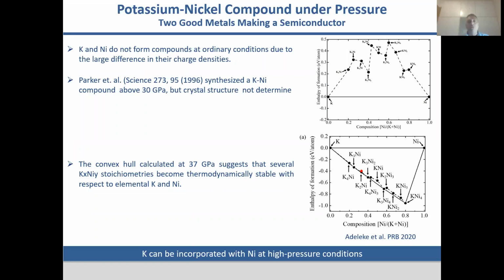Under pressure, we know that there is an s-to-d transition in the case of potassium, so it becomes more like a transition metal. And indeed, if we calculate the convex hull at about 37 GPa, why 37 GPa? Because back in '96, there was a paper by Parker et al. reporting the synthesis of a potassium-nickel compound just above 30 GPa. However, it was not possible to determine the crystal structure.